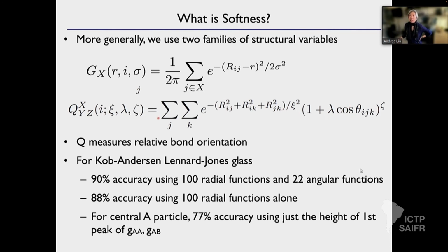But these three-body terms are absolutely necessary when it comes to training on something like silica, where you have tetrahedral bonding, and that bond angle information is really important. But for spherically symmetrical potentials, it's not.